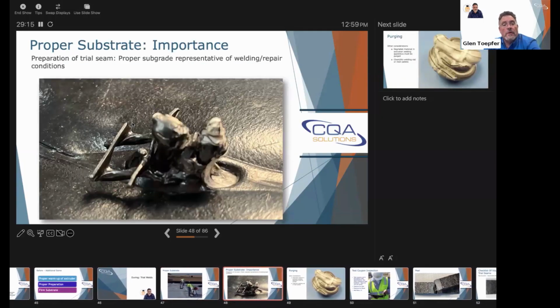And the importance here is shown in this photo. You can see this was actually cut out of a patch we took a destruct on because there was a sunken area, but they were overheating the tees, and in this case, the extrudate was overheated so much it forced itself through the underlying geonet and bonded with the geonet when it cooled. So it shouldn't be doing that. You shouldn't even be getting that overheat, but that would have had disastrous consequences with the expansion and contraction of the materials, as well as any stress that would have come on it during use.